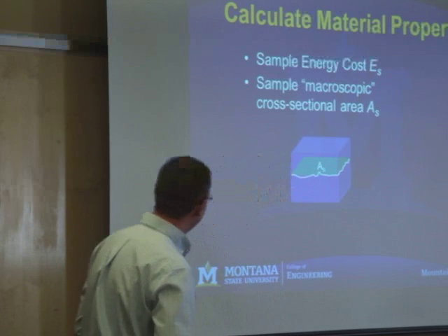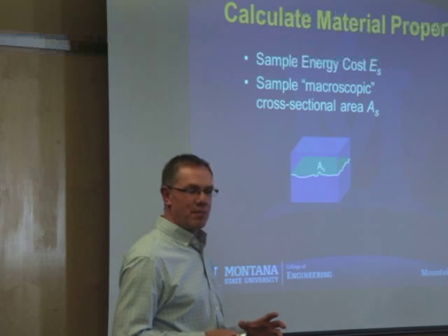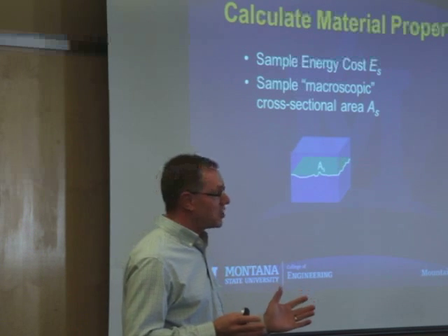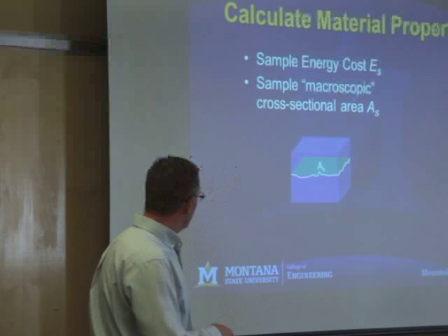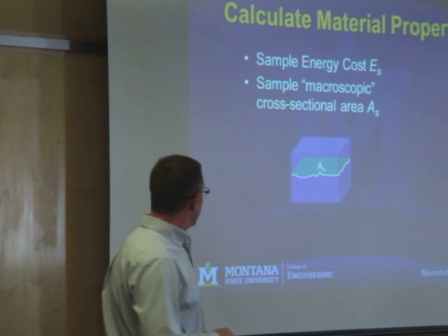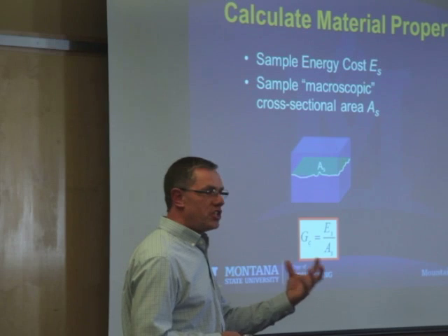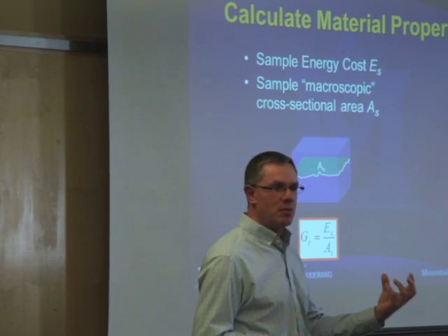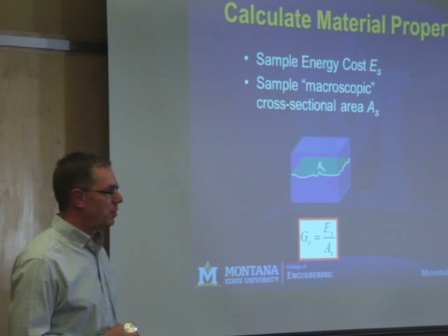Big is not big, okay? But we take a representative sample. How's that? A representative sample where statistically, and it really isn't hard with snow, it doesn't take a real big sample, where we can then find in 3 dimensions where this path is going to go. And then we add up the energy it takes for each of those bonds along that minimum path, and out pops that quantity, a prediction of that quantity that we want.